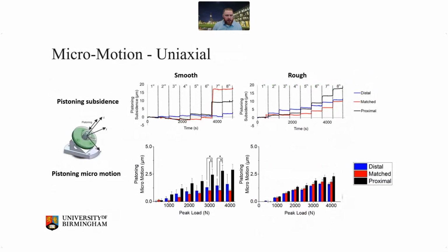I'll skip through this, but the take-home message was these tapers were described as self-centering, in that a surgeon can essentially knock a head on a modular taper, and it'll be fine. It'll just work. It'll work itself out. But what we found was that actually under uniaxial loading, so I didn't mention we did this under uniaxial, but also under the ISO profile.